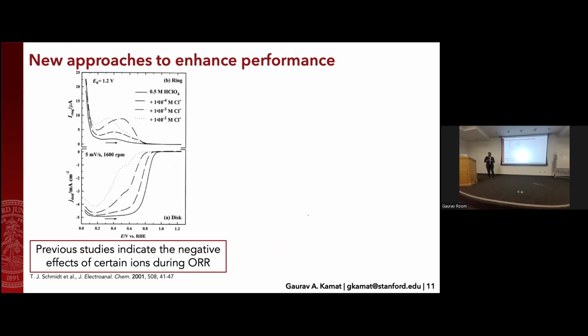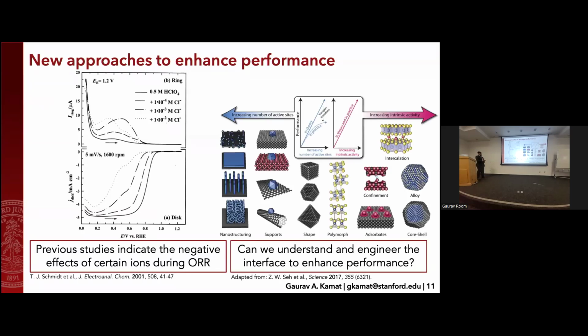So in the past, there have been some studies of this region, particularly with anions, and a lot of them just indicated the negative effects of certain ions being present. So on a platinum surface, if you have 0.5 molar perchloric acid, and you add very, very tiny amounts of chloride ions, we're talking even 10 to the minus 4 molarity compared to 0.5 molarity, you actually see this onset potential shift left. So your catalyst is getting worse because of competitive adsorption. But a lot of studies just left it off there and commented that certain anions are not really good for catalysis. But there's another way that I look at this, which is, can we understand and engineer the interface to actually enhance performance?